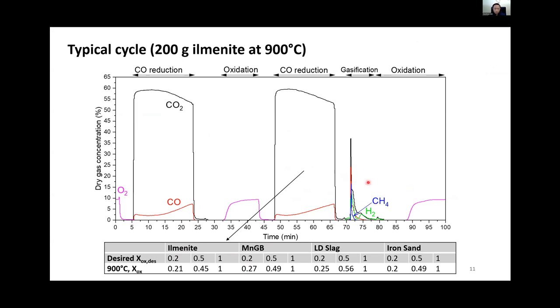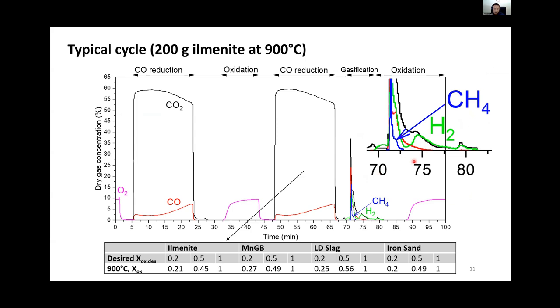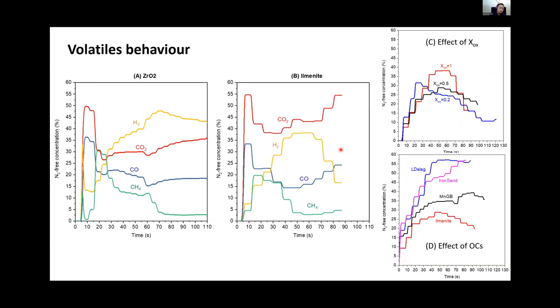And here, after a few injections, the volatiles release and char gasification happen. We divide the volatile release and char gasification by when the methane concentration ends. This is to facilitate the analysis of the volatile release and char gasification, so to say these two steps. First, let's look at the volatiles.